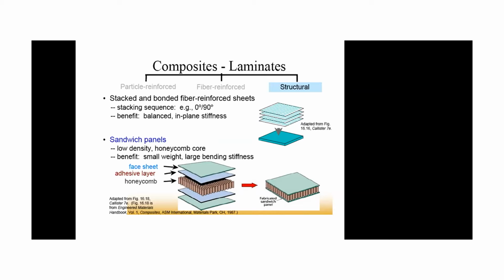Another is the sandwich panel. In first case, we are putting layer by layer all the component reinforcement as well as the matrix component. But in the sandwich panel, we are using one as a more in size, like we are using honeycomb core as a reinforcement, because it's a very high energy absorbing. And the matrix part is foam, and the reinforcement we are adding face sheet to increase its stiffness, bending stiffness, because foam can be crushed with the load, but face sheet can be deformed during the bending strength.